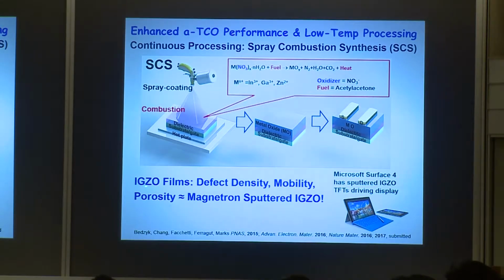driving the display. So if you spray combustion produce IGZO films, what are they like? What is their defect density like? What is the mobility and porosity like? This is by X-ray reflectivity and one other technique I'll show you in a second. They're quite comparable. So you can make IGZO quality films, like magnetron sputtered IGZO films, by this very simple spray, which we just do in a fume hood.